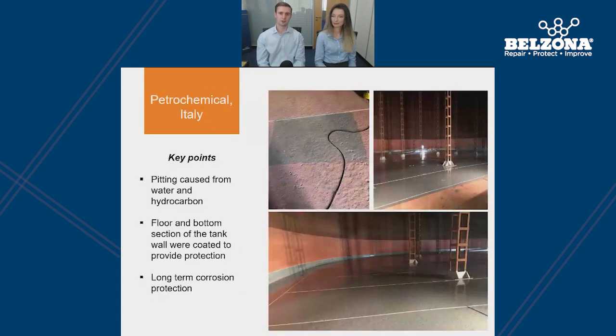Again, here we have a very similar problem in a petrochemical plant in Italy. A mixture of water and hydrocarbons were present within the tank, resulting in pitting at the base of the tank. The Belzona solution was to pit fill the localized damaged areas and to use an internal lining based off the operating conditions of the tank to coat the floor and also the bottom section of the tank wall again. So this type of repair is something that Belzona is very experienced in, and due to a wide range of internal linings, we can make sure the correct lining is selected based off the individual operating parameters of each tank.